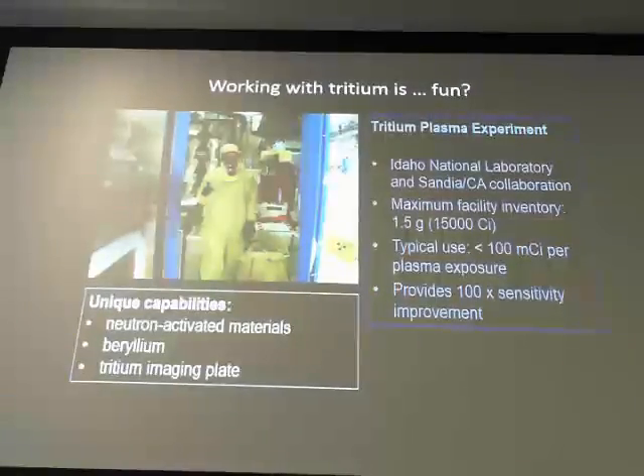For the case of looking at permeation barriers or permeation rates through materials, there is a small amount of atomic tritium in the gas that can interact with the surface, unlike deuterium and hydrogen, that can override a barrier to chemisorption on the surface. So permeation in a tritium environment may not be the same as what it is in a deuterium or straight hydrogen environment as a result.